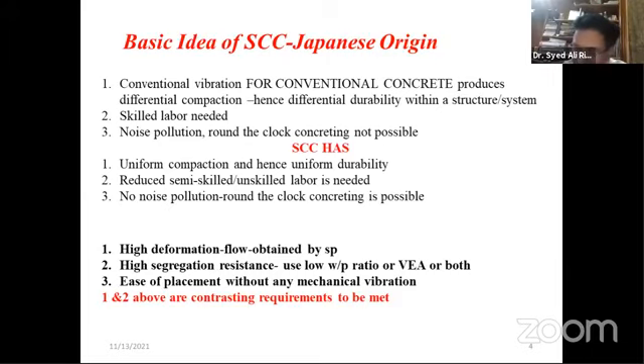And incidentally, in the early 80s, a quantum jump in material engineering took place when the high range water reducing agents were manufactured in Japan and Germany simultaneously. So they were able to reduce the water demand by 30%. So if you consider Abrams' law, water cement ratio versus strength, you know that as the water cement ratio decreases, the strength increases, or vice versa. But when the water cement ratio decreases, workability problems arise. So then these high range water reducing agents were invented, which allow us to work with very low water cement ratios or water cementitious material ratios, and yet have a lot of flow.